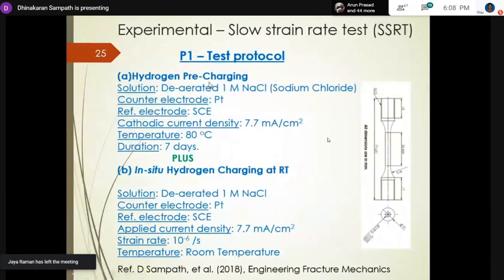The test protocol is hydrogen pre-charging, that means we use a three electrode system to have an electrochemical reaction generating hydrogen on the surface. We apply a cathodic current density of 7.7 milliamps per square centimeter. It's a constant current density based on the surface area exposed, at a temperature of 80 degrees for 7 days.